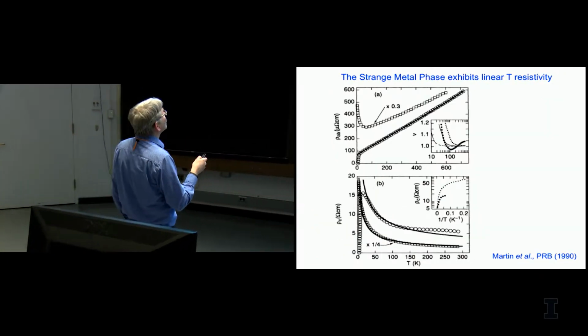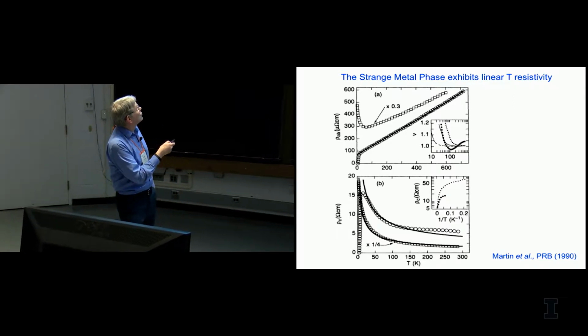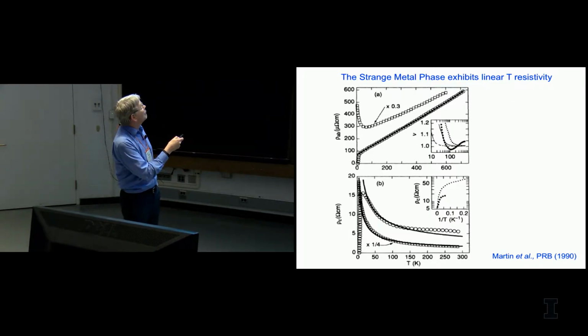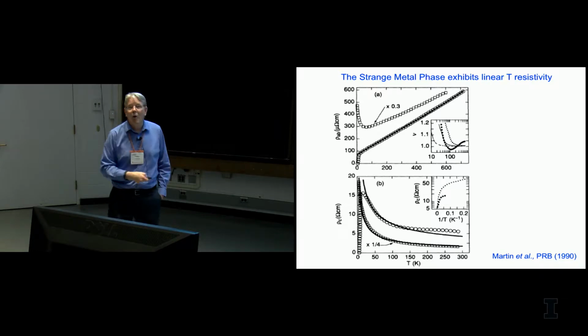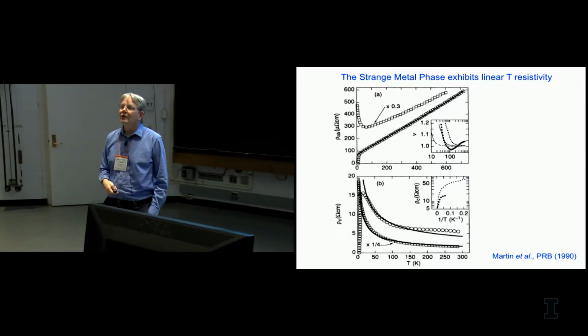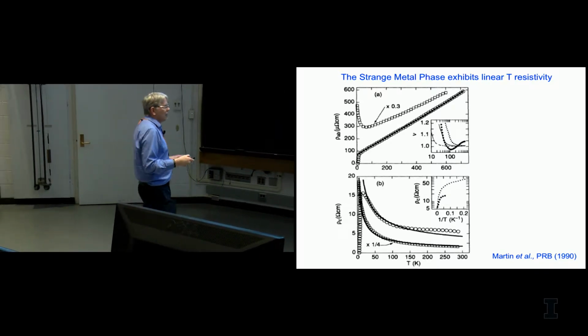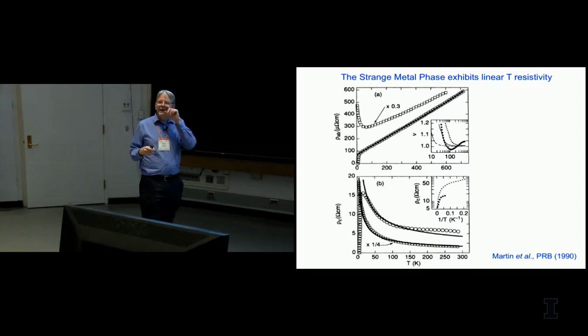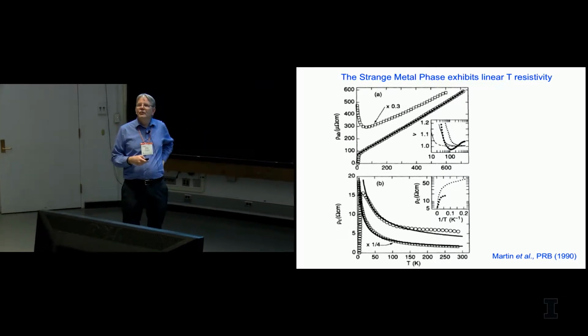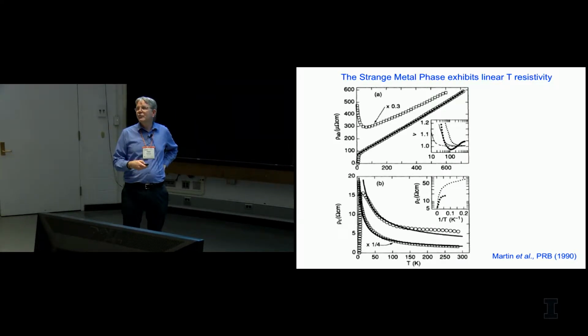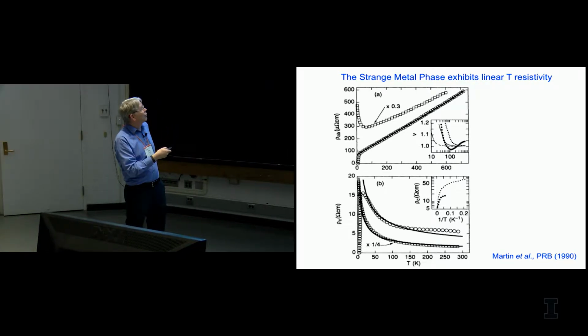These are transport measurements on single layer BSCCO, rho versus temperature, and you can see the linear variation with temperature extending over decades of temperature. So this is very unusual, right? Because resistance going like an odd power of temperature is a rather unusual thing that typically happens maybe at higher temperatures. You can have this, say, from electron-phonon interaction when you go to high temperatures, but to have it persist all the way down to low temperatures is very unusual.